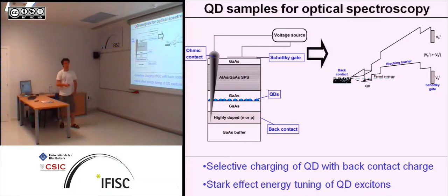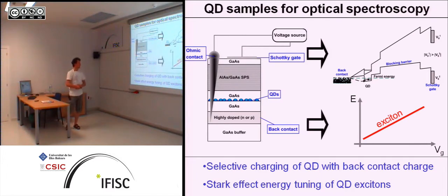And this is good for 2 things. The first is that you can use it to selectively charge a quantum dot. Here you have the highly doped region of the back contact. You have to imagine the structure physically going along this line. So you have the free carriers in the back contact with the Fermi energy. By applying voltage between back contact and Schottky gate, you can change the tilting of this band, and thereby change the potential energy of the quantum dot relative to the Fermi energy of the back contact. If you're at resonance with the Fermi energy of the back contact, you will get tunneling of one carrier into the quantum dot. You can play this game: lower or raise the voltage, and thereby you tunnel in or tunnel out. The next benefit of this structure is that you can use the DC Stark shift, and with that you can tune the energy of a single exciton in the quantum dot, which is quite important later on.